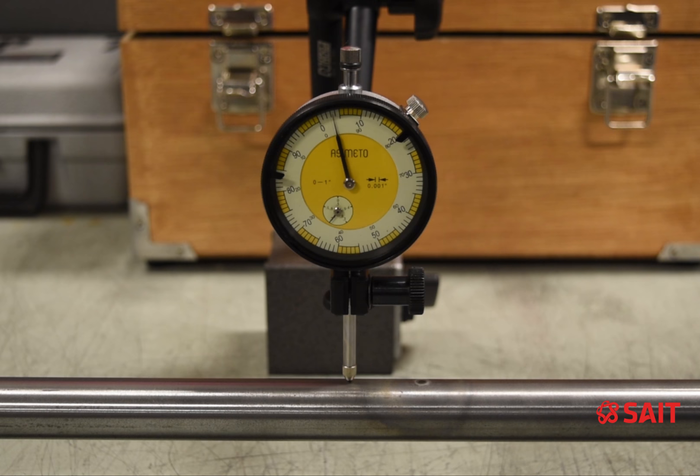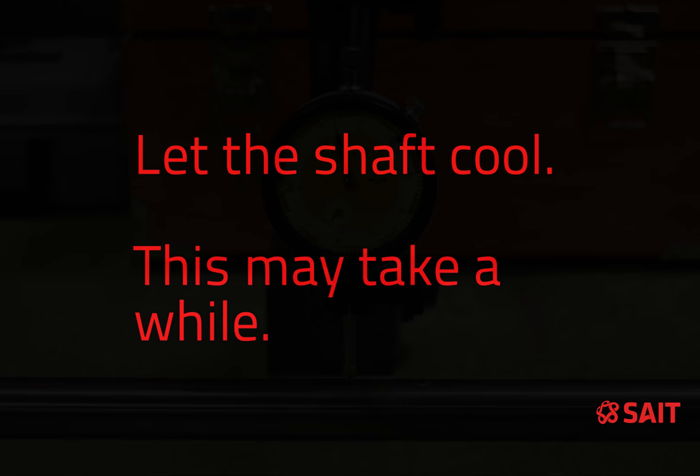We also want to heat quickly without heating the entire shaft. Using a small welding tip, we heat in one localized area for a short time so that we are only heating on the surface more than trying to heat up the entire shaft all the way through. We want to heat more to the surface only.